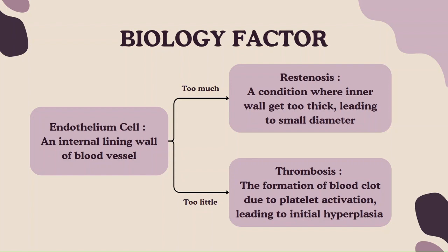However, if the vascular graft that is being deployed is unable to attract endothelium cells due to the surfacing or etc., it could cause immune activation by the platelets, forming a blood clot surrounding the internal wall of the vascular graft, which is known as thrombosis. And this is the worst one because it can cause arteriosclerosis or intimal hyperplasia in the long run.